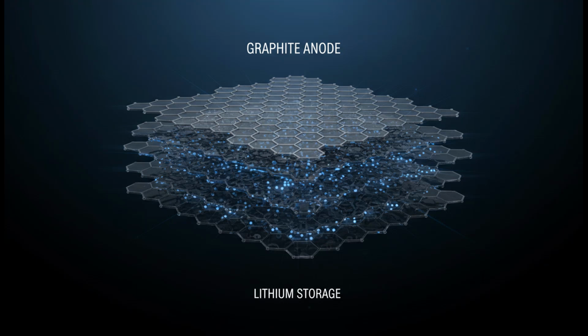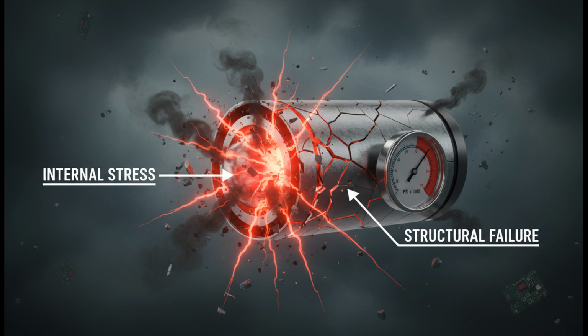To understand why this is so difficult, we have to look at the anode, the part of the battery that stores lithium when the car is charged. In standard batteries, we use graphite, which is reliable but bulky. If you want more energy, you'd think you could just use pure lithium metal. It's the ultimate anode material, but it has a fatal flaw. It expands and contracts violently during every charge cycle. This expansion is like trying to inflate a balloon inside a steel box. Eventually, the pressure becomes too much, the materials crack, and the battery fails. This is the strain problem that has haunted engineers for years.